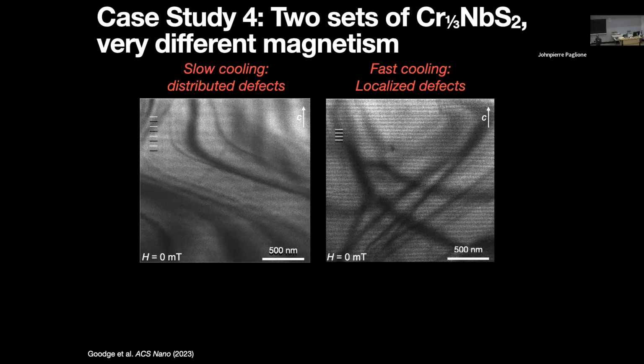But they showed, and this is a Lorentz TEM, so it's an electron microscopy image where we are sensitive to the magnetic texture of the material. We're basically imaging that helimagnetic winding. The more dominant bands that you see that are curving and waving are just associated with the lamella of the FIB cutout of the material. But what you want to pay attention to are the horizontal stripes, which are a little bit fainter, but you can see that they're tighter on the right versus on the left.